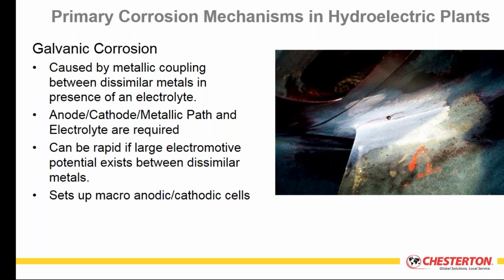Now, where would we see this? An example is shown on the screen where you have a hydro runner where they may have done some weld repair. In that region of weld repair, they've used a different alloy, maybe not the same alloy, or the quality of the weld was insufficient, and you've now generated an anodic cathodic region in that weld zone, and that can cause significant issues because the anodic material will fail more rapidly than the cathodic material.